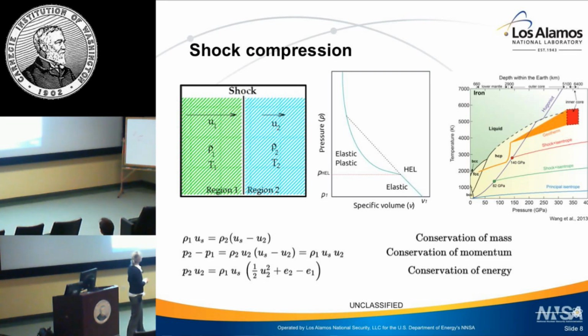For instance, here is the temperature-pressure diagram for iron, and in purple is an example of a Hugoniot. There are particular high pressure states that one can access using shock compression, combined with ultra-fast X-ray probes to determine structure and other material properties.